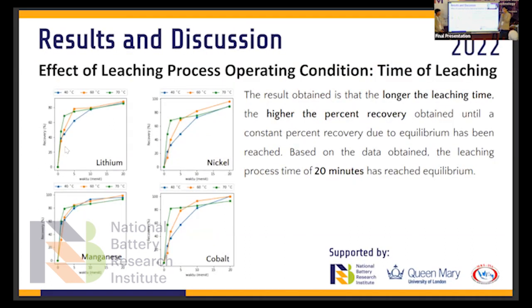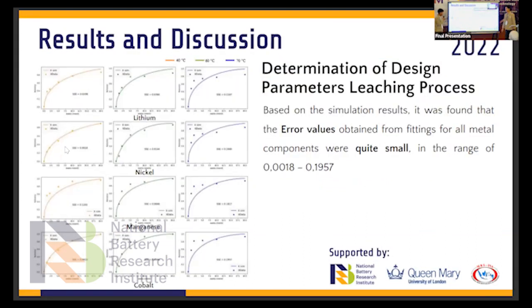For the effect of leaching time, the longer the leaching time, the higher the percent recovery we can get. We can see in this graphic that we get a constant value. It means that equilibrium has been reached. Based on this data, the equilibrium time is 20 minutes. And after doing a simulation for the experimental data, we get this graph. From the graph, the SSE result is quite small, so we can conclude that our mathematical model can be used to represent the leaching kinetics.